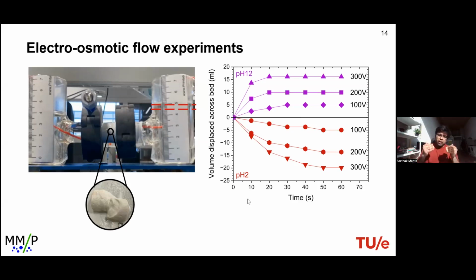So we have a graph here that gives us the time dependence of electroosmosis under different pH conditions. We can see that for pH 12, the flow is in the right-hand side or positive direction, whereas for pH 2, the flow is in the negative direction. That is because the silica particle polarity changes between these two pHs.